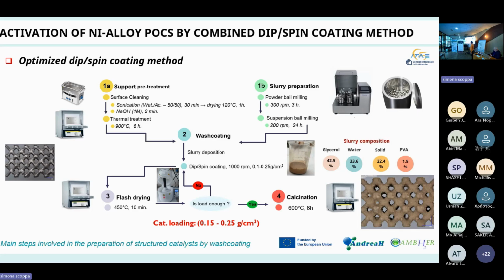So coming back to the coating methodology, the dip and spin coating method. It's not so complicated. It's a very scalable method in which we need an initial thermal treatment of our support in order to generate some oxide on the surface that helps the bonding and the stability of the catalyst. In parallel we prepare a slurry, a special composition using some binder, some dispersant, glycerol, water and a solid amount, and then we make two kinds of operation. One is dipping, and the other one is spinning, in order to remove from the support the excess of slurry.